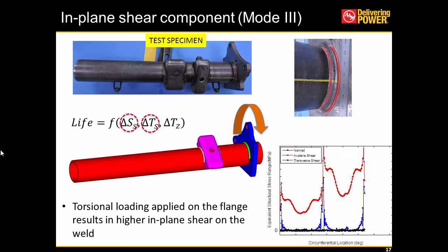Now let's look into a second case, a brake flange weld, where it is subjected to a torsional loading. This is the case where we were talking about throat failure. In this particular case, we observe a very high in-plane shear component. And there is also a normal component because of the gaps present between those two components and also the non-symmetry of the brake flange.